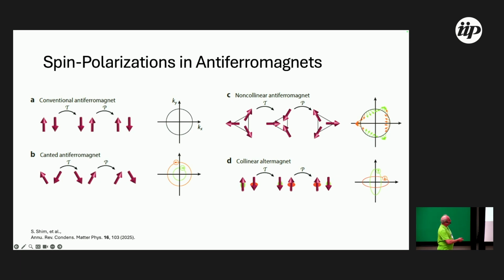We just talked about these collinear altermagnets, where you have this because there's different local symmetry around the two sublattices. But you can also have non-collinear antiferromagnets, and if you go through time and parity reversal, you don't end up with the same thing. And lo and behold, you also get a momentum-dependent spin polarization of the electronic band structure there. So these kinds of things can be fairly common, and this is maybe more the exception to the rule. Why this has a different name from this, I don't know. I'm not even sure.